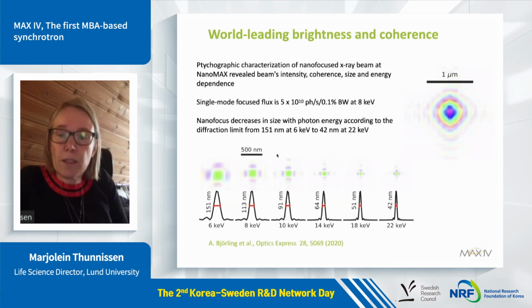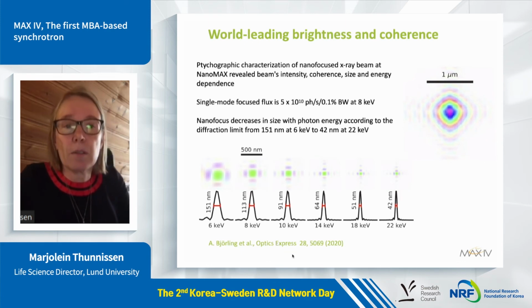One of the first things, of course, when you build new beamlines is to do a full characterization. And this is a full characterization of the beam using ptychography, and it really highlights that we can produce a very nice nanometer beam with a very high flux, but also a very high amount of coherence. So the coherent properties of this beam are really, really good. We were very pleased with this characterization, which has very recently been published in Optics Express. And it shows that the concept that we have been using really works, which is very important.